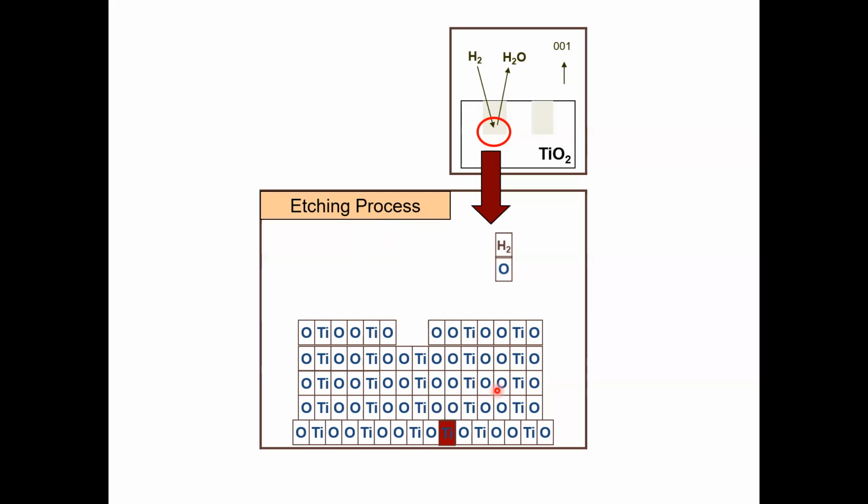So there are some internal sinks. One titanium can be accommodated per 800 units. So in the bulk, there is plenty of titanium sink. As oxygen is taken out, titanium moves into the bulk. So you create a gap, and that is creating this empty space between fibers.